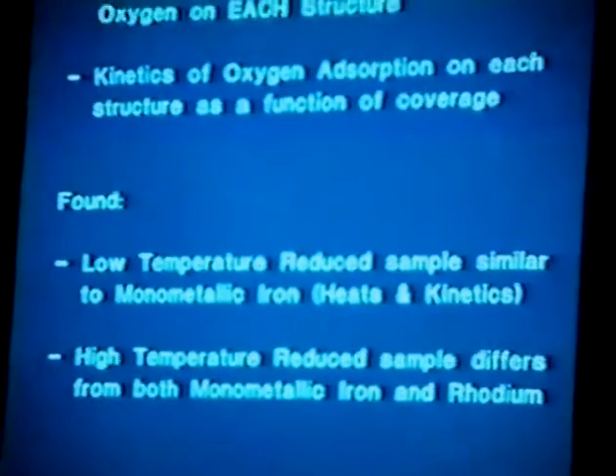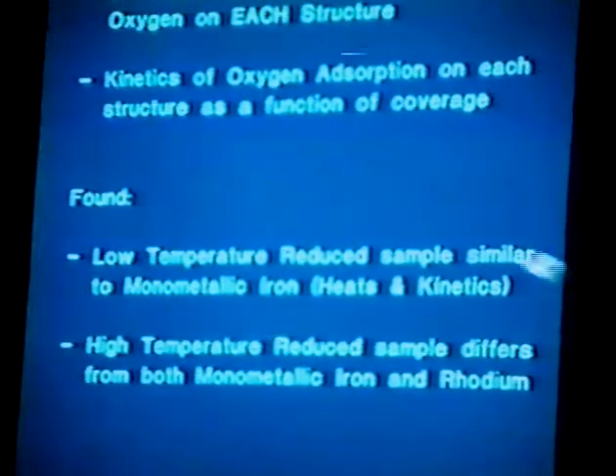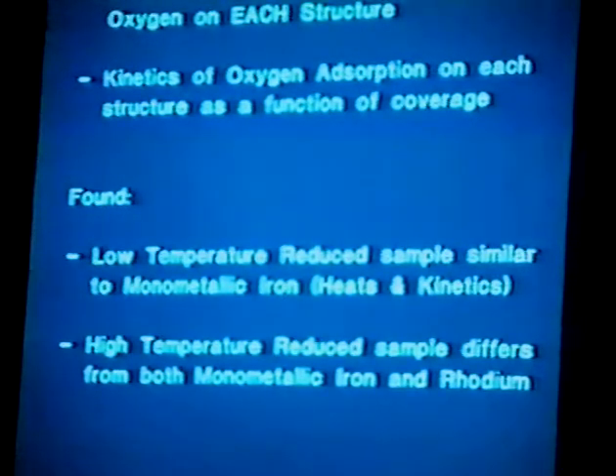What we found was that when we adsorbed oxygen on what I'm going to call the low temperature reduced phase, the segregated reduced metal phases, the heat profile was essentially the same as what you would see on monometallic iron. Whereas if we adsorbed oxygen on the previously high temperature reduced and alloyed particles, the system exhibited behavior that was not like either of the monometallic extremes, and it was very characteristic of what we believe is a bimetallic, uniform bimetallic alloy phase.